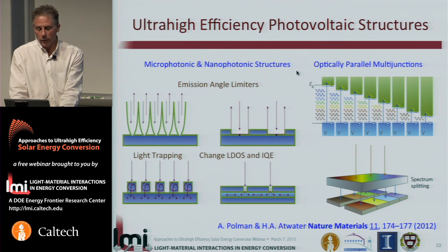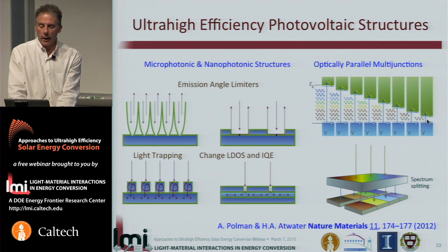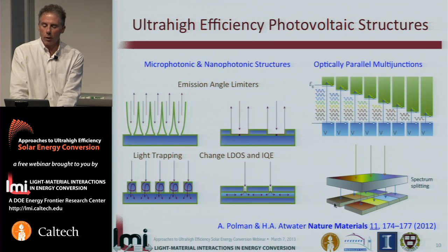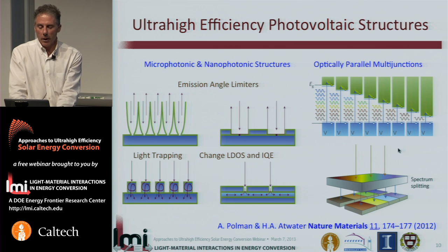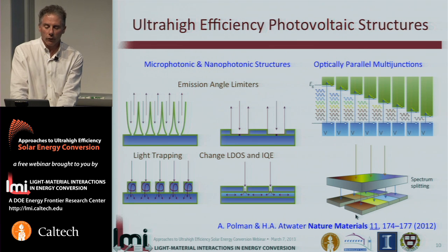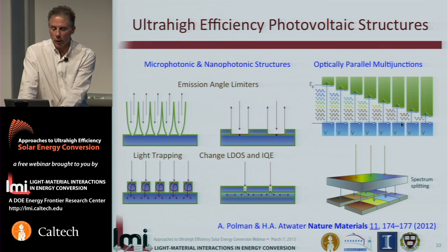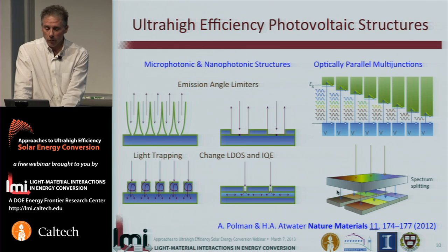And then, of course, the energy losses due to thermalization of photons could best be managed by thinking about making multi-absorber cells where, instead of, as in conventional multi-junctions, where we have 2 or 3 absorbers, we now proliferate the number of individual absorber layers in a cell and are able to split the solar spectrum such that a spectral band that's well matched to each absorber and its optimal absorption coefficient is able to distribute the entire solar spectrum among this array of optically parallel cells. Then much higher efficiencies could be achieved. And of course, this requires a photonic design of this spectrum splitting structure as a critical element for success.